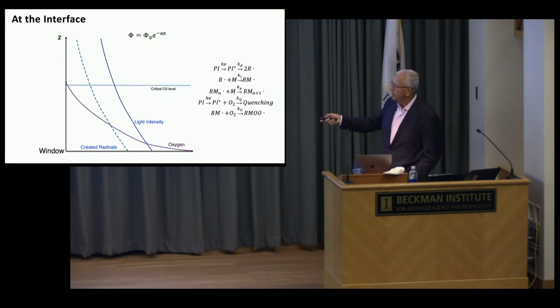This is a generic concentration axis down here, and this is the z direction from the window up into the resin. We have a liquid resin that's got a polymerizable monomer and a photoinitiator. We have light coming through the window. Light is at its most intense in the resin as it exits the window, because that's the source of the light. And then the light intensity decreases with distance up into the liquid just due to the molar absorptivity of the resin. It's like shining a light into murky water, right? It's dissipating with distance. That light is decomposing a photoinitiator that's generating a radical pair. So the concentration of radicals basically tracks with the light intensity.